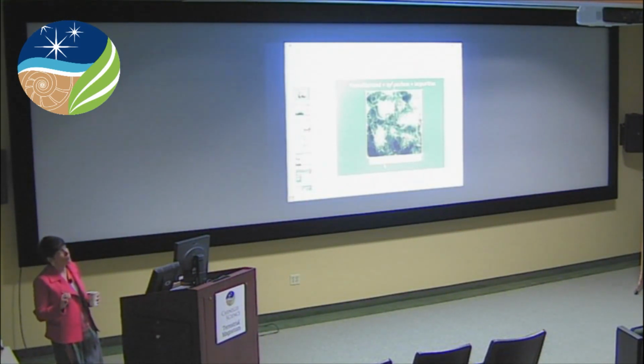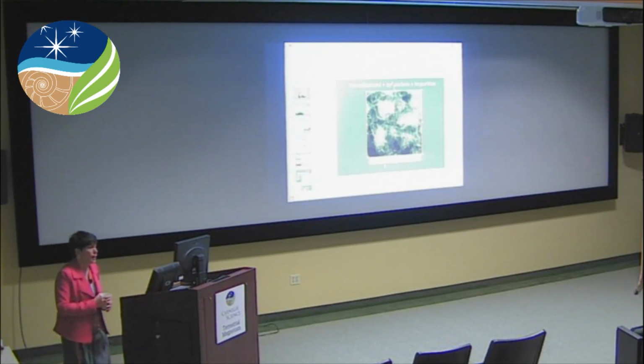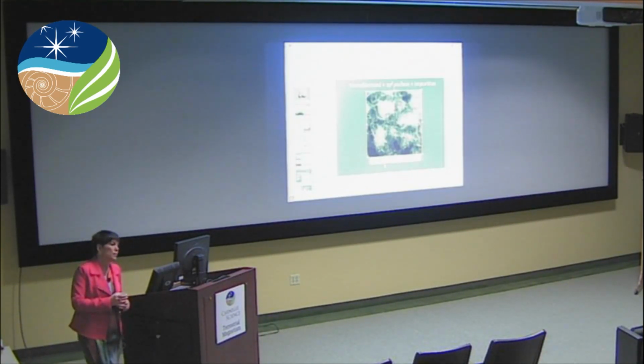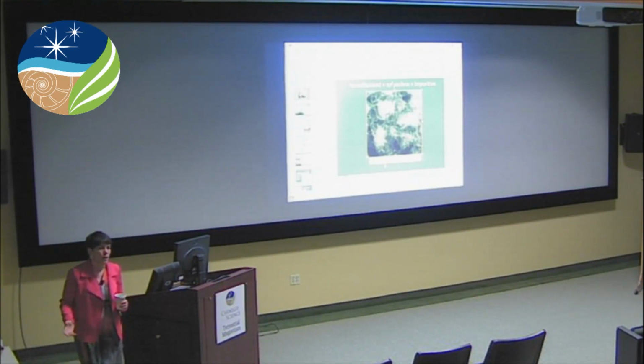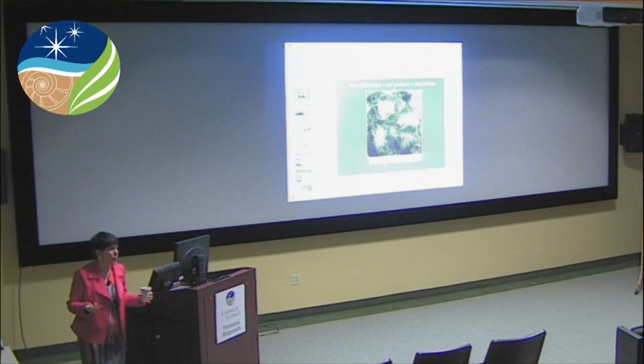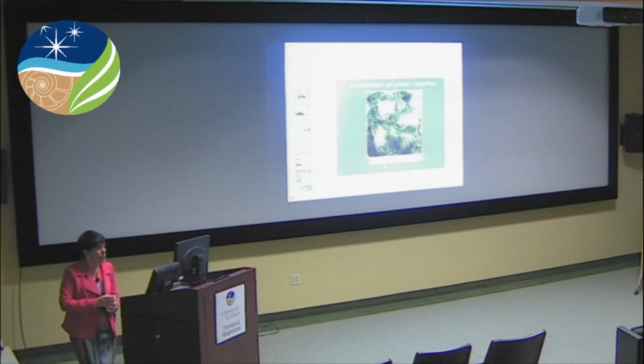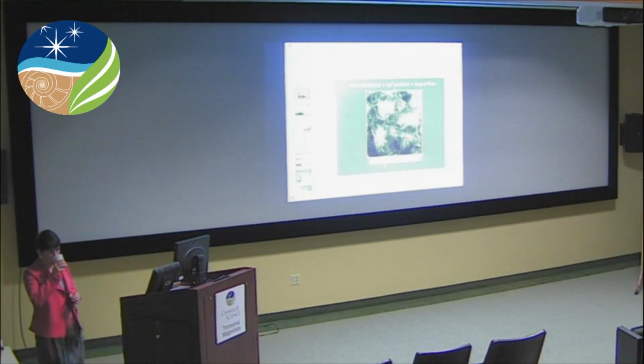Let's play it. Right. Okay. So the image intensity of each of those individual spots is indicative of its atomic number. So a large fraction of the ones moving here are silicon, but not all of them. I think there's also sulfur. I've seen some phosphorus. I've seen tiny nanoparticles of palladium. So there are refractory metal nuggets, less affected by the acid dissolution, that can get dispersed in here. So a lot of different species.